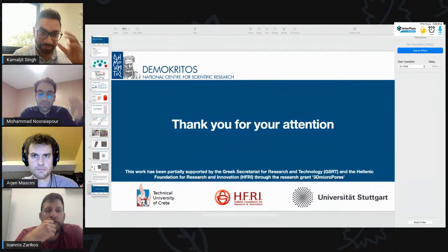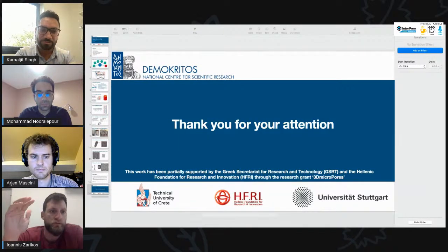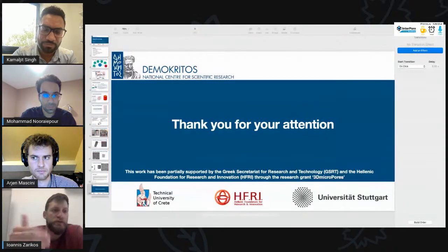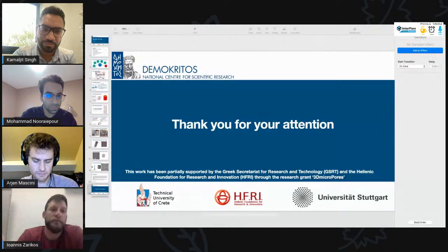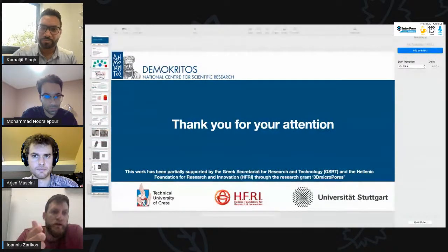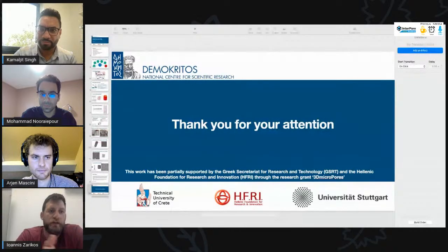In this case, it could be 20 centimeters tall. It would be okay, but then it has to do with the CT scanner, if we can actually scan it nicely at a relatively high resolution. We can reduce resolution to scan a large sample, but small pores we're not going to be able to visualize. So it has to be a combination of both CT scanner and 3D printer. We can go large, but then it's up to the CT scan to visualize it.